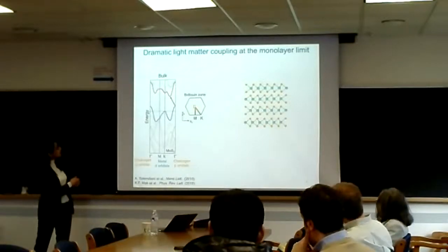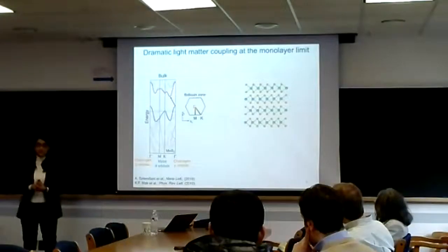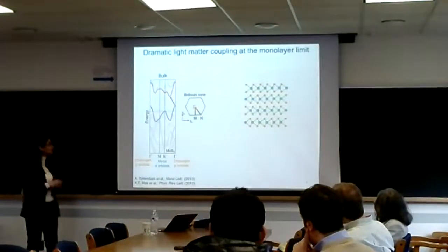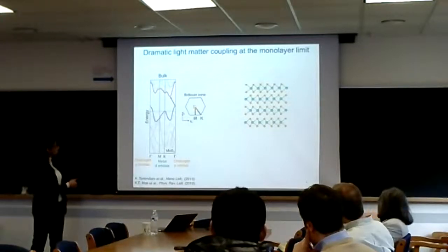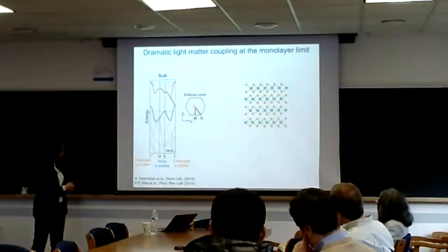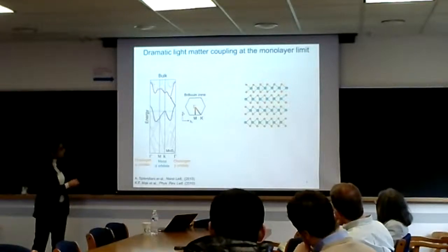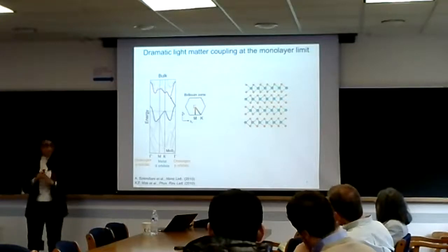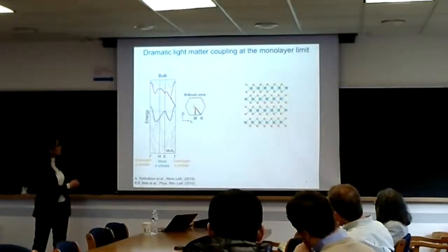But one of the reasons why MoS2, which is a fairly old material, there were reviews in the 70s on the excitonic properties of these materials in the bulk system. They're indirect gap in the bulk material. So this is the layers of MoS2 stacked on top of each other, looking at it from the side. The gamma point has contributions from the chalcogen p orbitals, which are sticking out of plane. So these are the chalcogen atoms like sulfur or selenium. And high symmetry points like the K point, M point, etc. have metal d orbital contributions that are in the plane of the material. So let's see what happens when you make this thinner and thinner, and many of you should be familiar with this, since one of the first demonstrations was done here about 9 years ago.